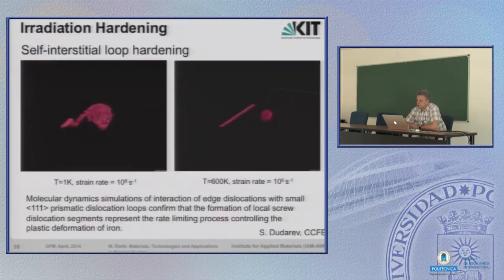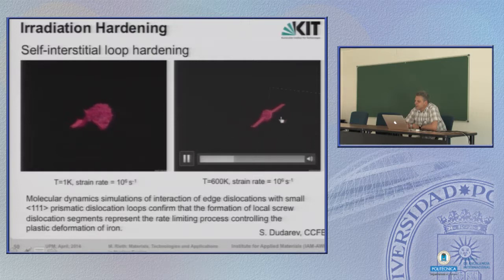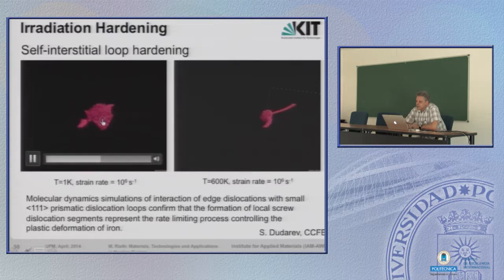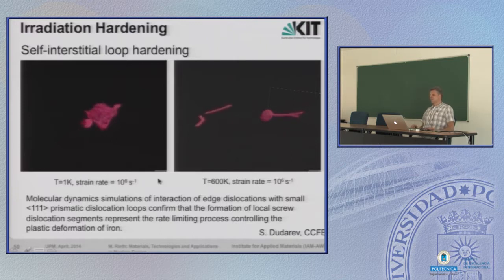Here again are two MD simulations where a dislocation glides along its glide paths or glide planes, and at lower temperature, here 1 Kelvin, it ends up at an obstacle. This obstacle is a dislocation loop, and at higher temperature you can see that the dislocation can more easily go through this dislocation loop, which means at low temperature, all this irradiation hardening is more pronounced.